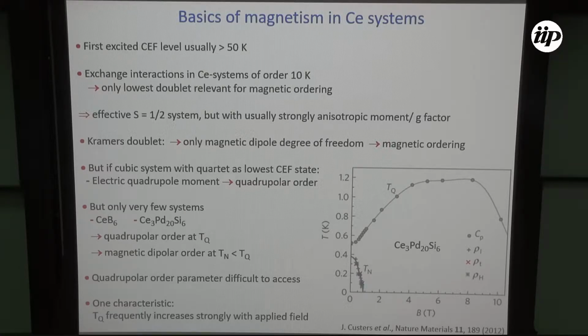The systems which have been very heavily investigated are CeB6, for 30 or 40 years, and more recently Ce3Pd20Si6. Both show quadrupolar order. Here is the phase diagram of the latter compound, temperature as a function of magnetic field. If you cool down, you have first the quadrupolar transition, and at lower temperature an antiferromagnetic transition. Quadrupolar order is very difficult to access because you don't see a signal in neutron scattering at B equals 0. If you apply a large magnetic field, some magnetization appears and then it becomes visible.